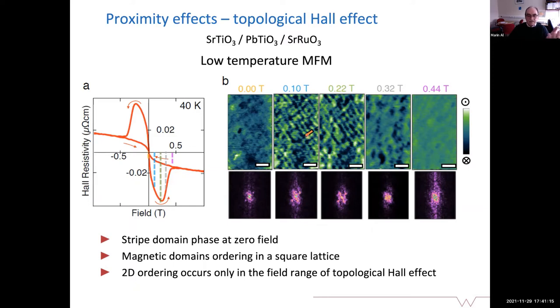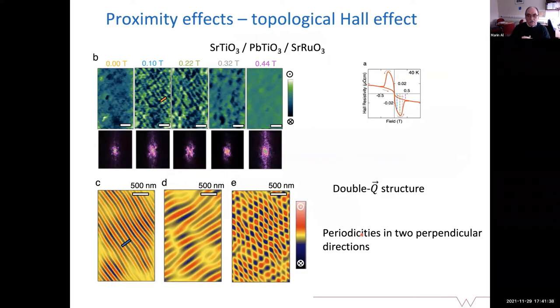Because the spacing between these is quite small. It's about 100 nanometers, or this is a micron here or a quarter of a micron, I don't remember exactly. So it is also relatively small for a magnetic domain. And then we analyze, of course, and we arrive at the conclusion that it should be a so-called double-Q structure. We have a periodicity in 2 perpendicular directions. So you see, this is one periodicity if we select only one peak of the Fourier transformation. And then we have another one, which is not that nice. But all in all, we have this nice periodicity.